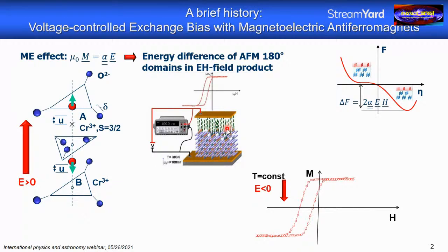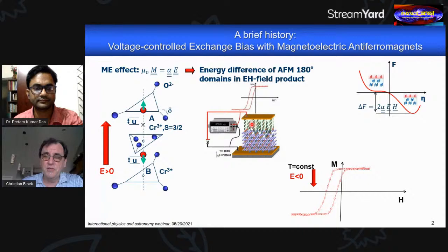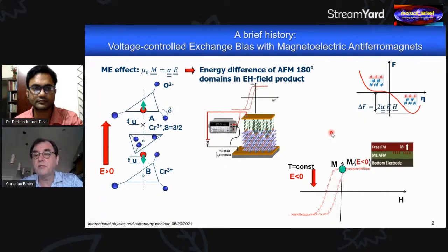There are two components to it. So whenever you have a ferromagnet exchange coupled to an underlying antiferromagnet, you may observe the phenomenon of exchange bias, which is manifested in the fact that the hysteresis loop of this ferromagnet is shifted out of the center of this magnetization with this field coordinate system. And typically it's shifted to negative field values, and that shift we call the exchange bias field. Now in this voltage controlled system, we can switch the orientation of the antiferromagnetic interface magnetization, the boundary magnetization, and therefore we can switch whether this shift is negative or gives rise to what we call positive exchange bias.